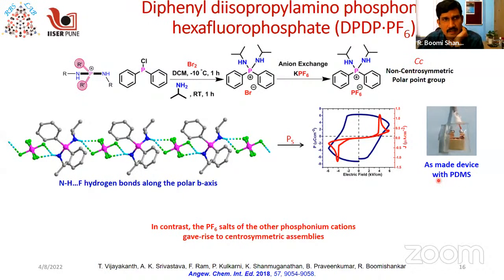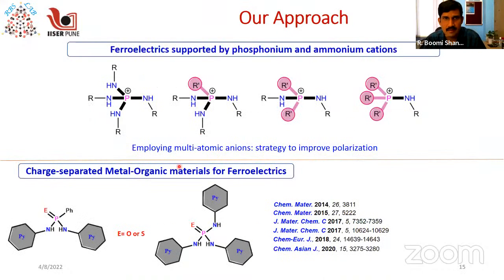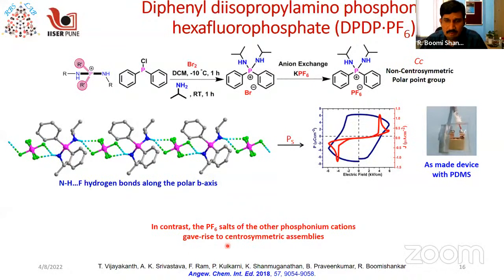But what we have to understand is that when we had this diphenyl and diisopropyl system, the PF6 salt was non-centrosymmetric. But for the other cations like the phenyl triisopropyl or triphenyl isopropyl phosphonium compounds, the PF6 salt was found to exhibit centrosymmetric space groups. This is because the PF6 is octahedral and has an inversion center, and therefore the structure dominating force was played by the PF6 anion instead of the cationic phosphorus compound.